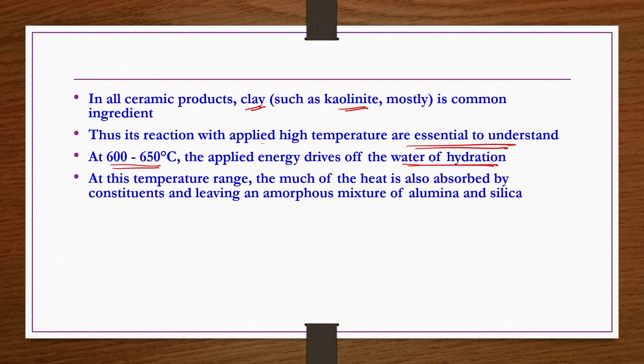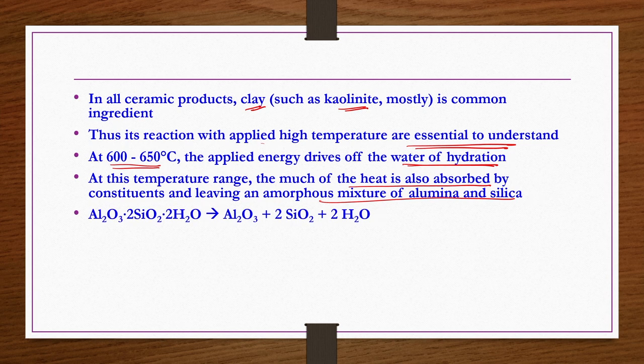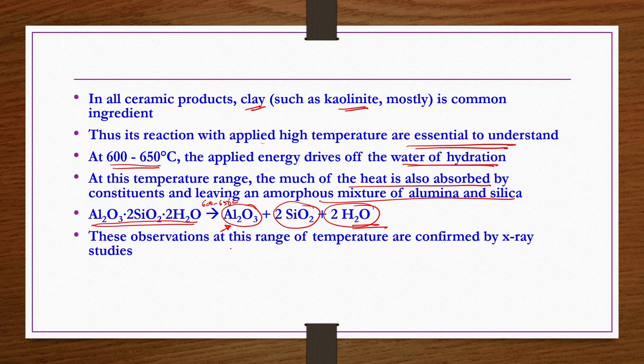Further, at this temperature, what happens? Much of the heat is also absorbed by the constituents, leaving an amorphous mixture of alumina and silica as per the reaction. Let us say you have kaolinite and supply a temperature of 600 to 650 degrees centigrade; then you get amorphous alumina and amorphous silica along with water vapor. So not only does dehydration take place, but the individual components of the mixture, alumina and silica, are obtained in amorphous form. These observations at this range of temperature are confirmed by X-ray studies.